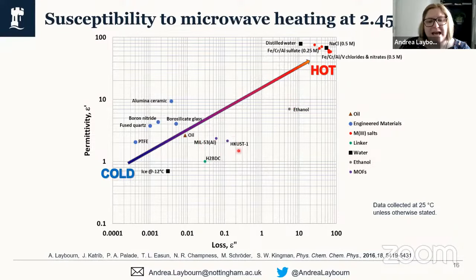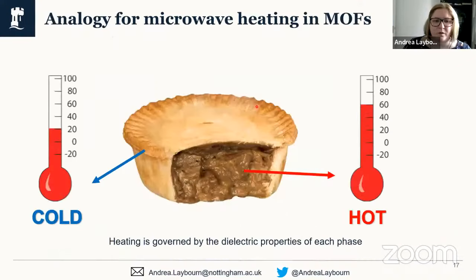Now, the MOFs themselves and the linker here, I've shown terephthalic acid as the linker. The same is true for the trimesic acid linker. These have medium dielectric permittivities and quite low dielectric losses. And so these will stay relatively cool. And so it's the solvent and the solvated metal ions that will be heating from these dielectric properties measurements. That would be our hypothesis.